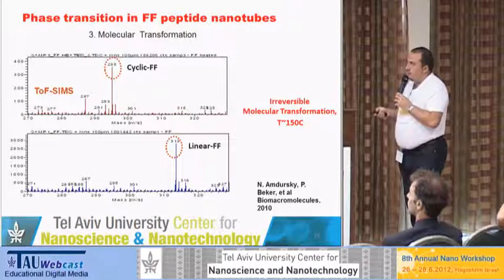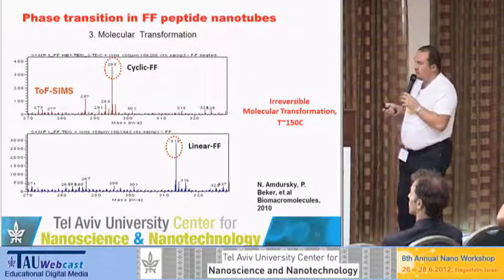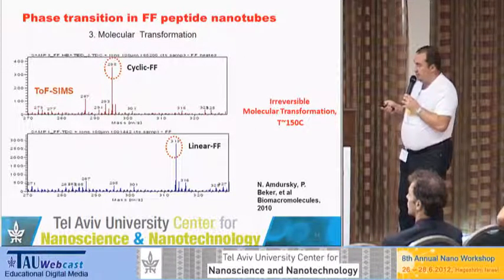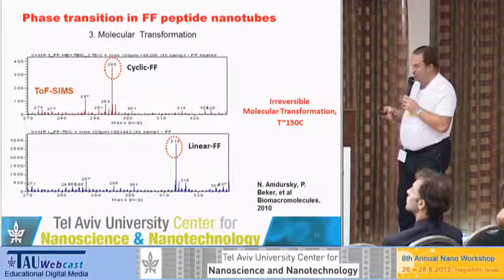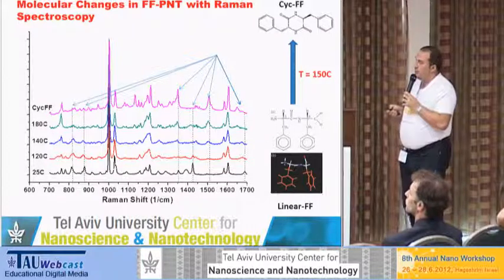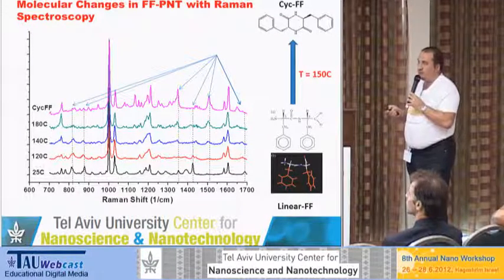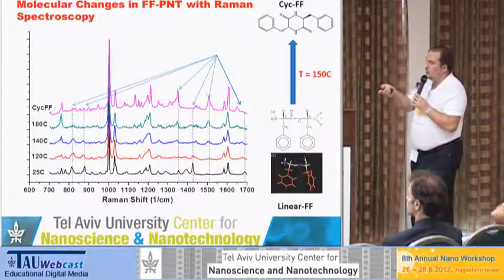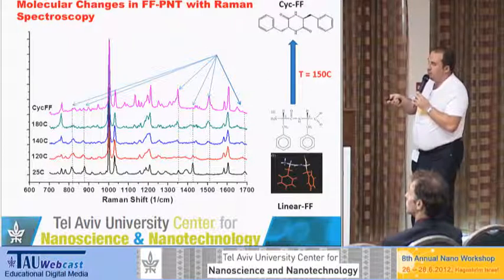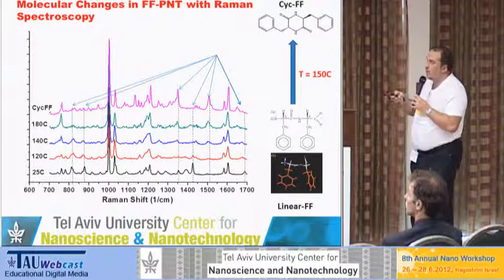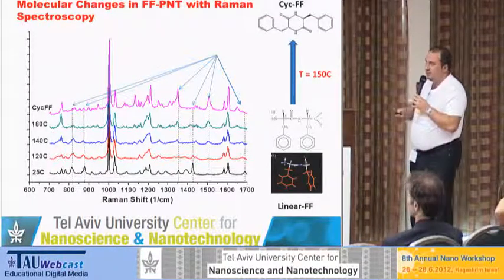diffraction. And what was measured previously is that at a temperature of about 150 Celsius, there is a transition from linear to cyclic nanotube, but it was not done at single tube level. Here we used Raman to acquire a spectrum from a single tube, whereas we increased the temperature. This is the cyclic spectrum, linear spectrum. As you can see, during the heating up to 180 Celsius, different peaks, some of them grow, some of them decrease, some of them shift. Finally, the spectrum gets indeed closer to the cyclic, which is further support of this finding at a single